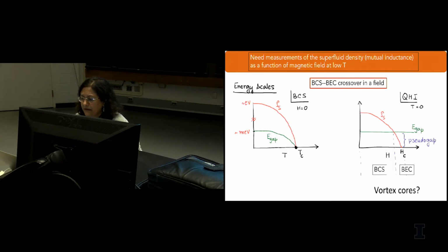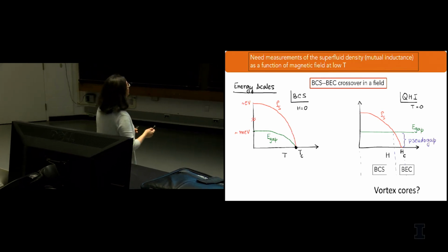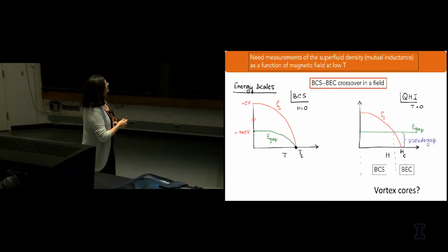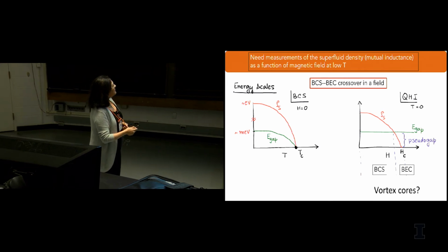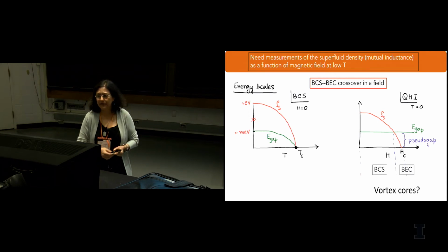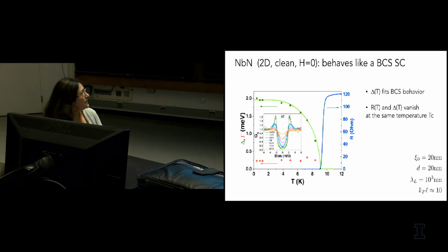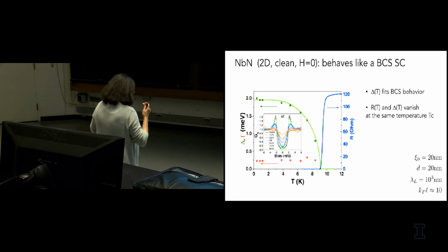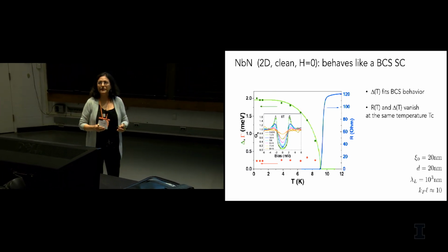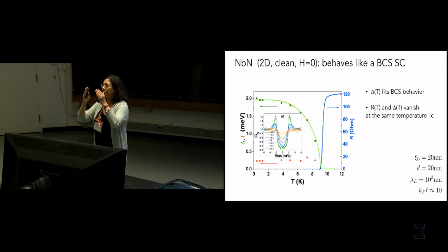Okay, so here is another prediction we are making. Just as we saw the gap persisting with disorder, now with magnetic field also the gap persists, the superfluid density comes down, and there is this region where you get a pseudogap now opening due to magnetic field, and we expect the vortex cores to have different behavior in these two regions.